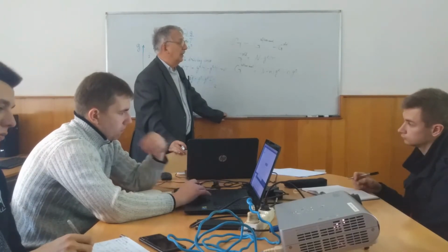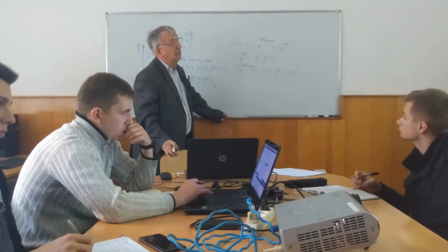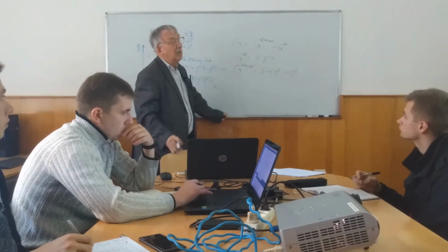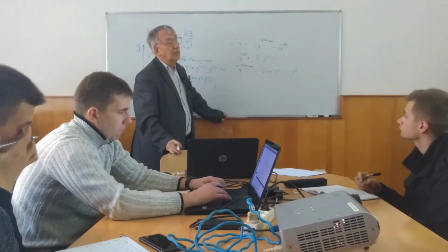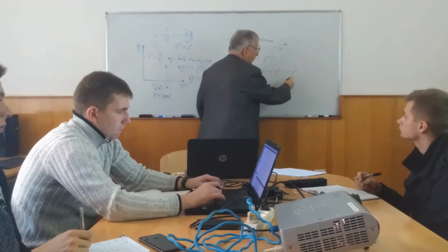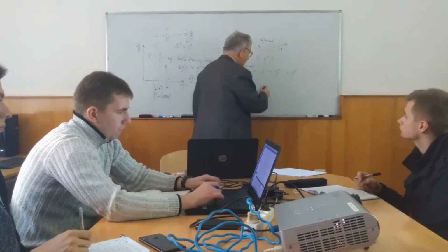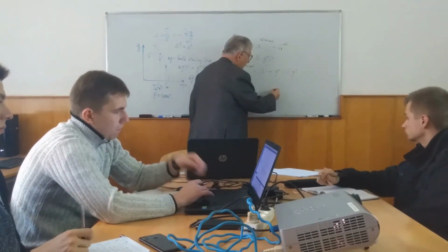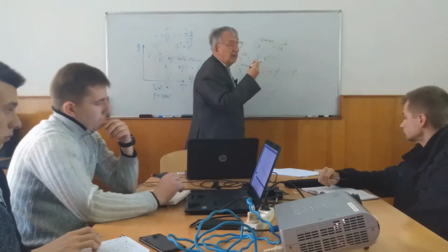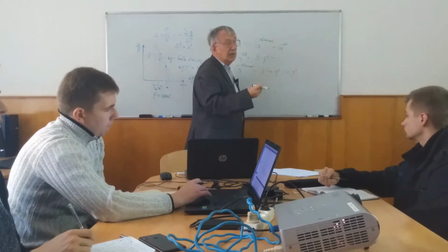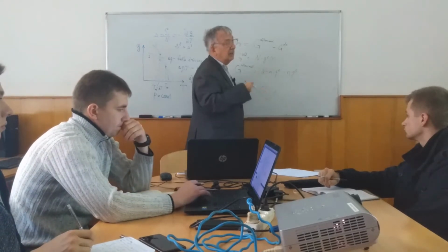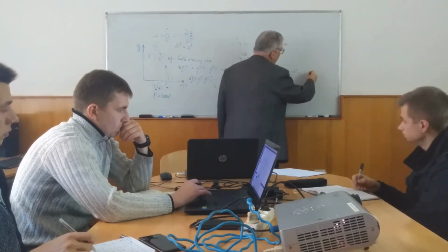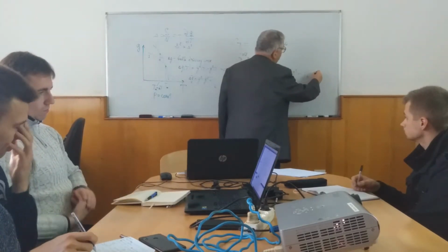But I remind you that this is, of course, a favorable event, but for any favor we used to pay. Here we pay for this favor by a surface term. Due to the bulk term, the Gibbs free energy of the system goes down. But of course, if we have some nucleus, some region of the new phase, which is crystal, and around we have liquid, it means that we formed the interface. And an interface is a defect, and a defect usually has additional internal energy and Gibbs free energy. So we add the third term, which is gamma SL, multiplied, if we take spherical form, by 4πr squared.